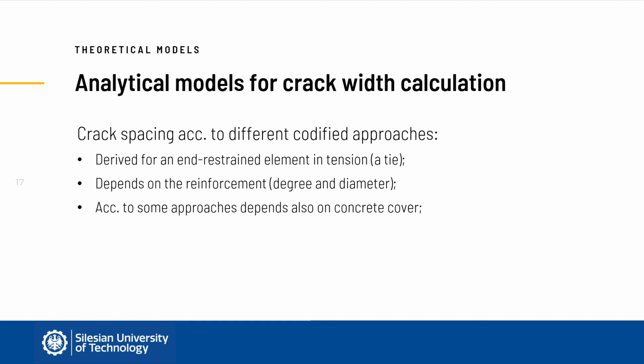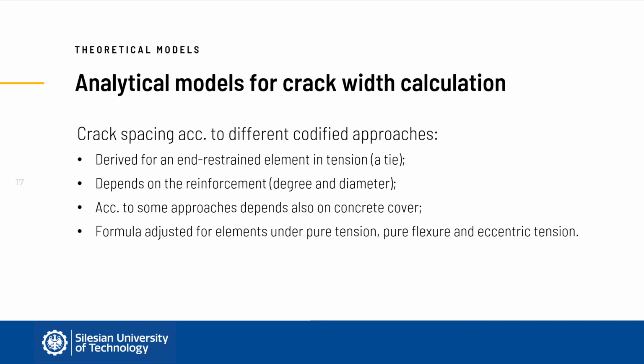bars. According to some approaches, the crack spacing depends also on concrete cover, although there is no agreement between the methods on this. The formula which is derived for crack spacing in an end-restrained element is further adjusted to represent any element under tension, so not necessarily pure tension, but also pure flexure and eccentric tension.